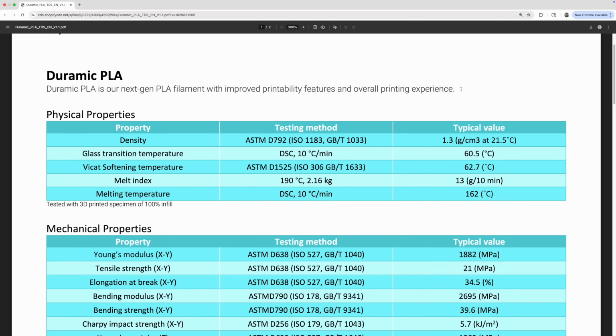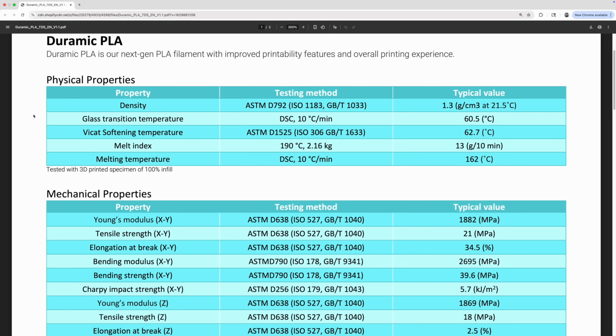This hotspot is actually really hot. I measured it during the test, and this area on the desk is actually hotter than the inside of the housing. So it's a pretty good torture test. While I was waiting for the test to finish, I looked up the actual glass transition temperature of this PLA, and I was way off. It's not 50 degrees, it's 60 degrees.